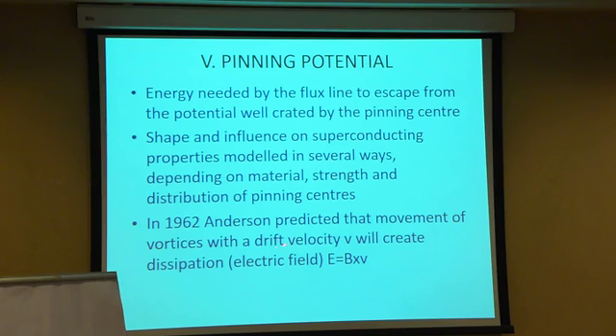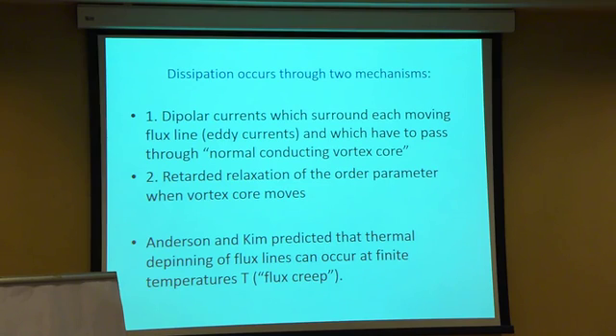In 1962, Anderson predicted that movement of vortices with a drift velocity v will create dissipation, and this is given by this. Dissipation occurs through 2 mechanisms: dipolar currents, which are eddy currents surrounding each moving flux line and which have to pass the normal conducting vortex core, and the second one, retarded relaxation of the order parameter when the vortex core moves. Now, Anderson and Kim predicted that thermal depinning of flux lines can occur at finite temperature, and this is called flux creep.